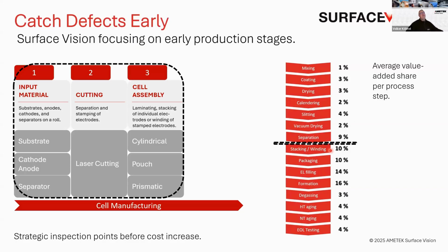And saying this, there is quite a big step from here to here on the value. And the reason is, when you find defects early in the process and you can reject or correct the quality before it enters the stack, then you only waste material cost and labor, I would say. But when it goes into the stack, it will then be much more expensive to reject the product later in the process. So this actually we define as a very strategic point to make a decision if a monocell or half cell or separator material is allowed to enter the stacking and the winding process.